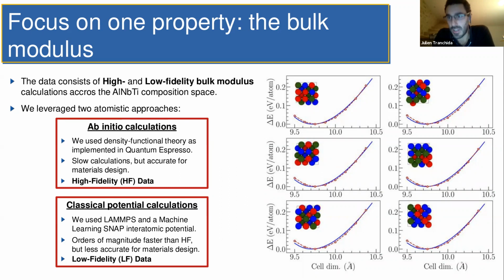First, ab initio calculations, as I told you. In that case, not to build a training set, but to do the actual bulk modulus calculations. So we still use density functional theory as implemented in Quantum Espresso. The calculations, of course, are much slower, but rather accurate. That's going to be our high fidelity data. On the right, you can see a typical equation of state we're going to be computing. It's basically the variation of the energy versus the fluctuation of the volume of the cell. All those 6 configurations are at the equicomposition point, but we did the same calculation at all the configurations.